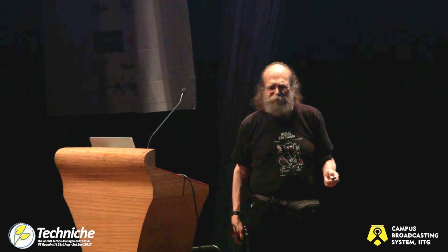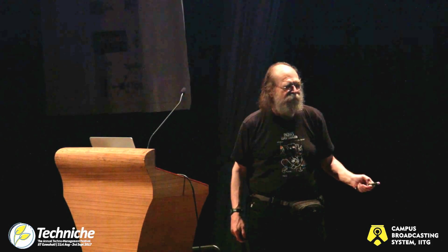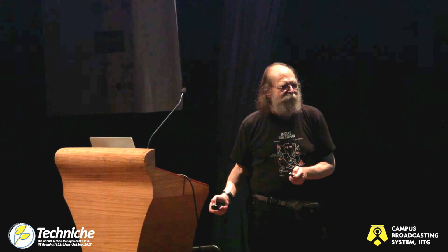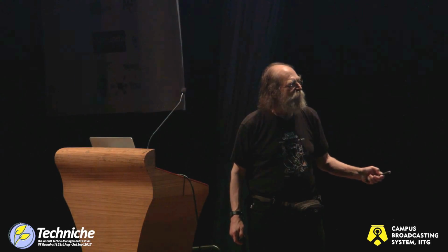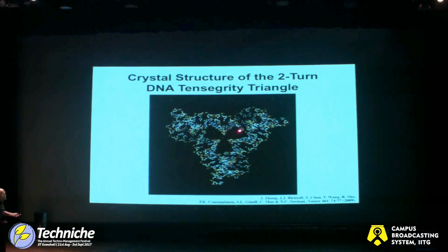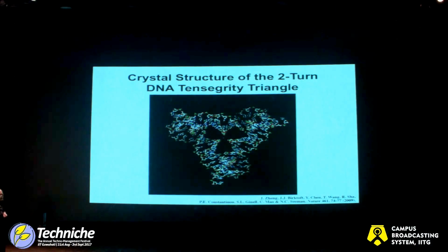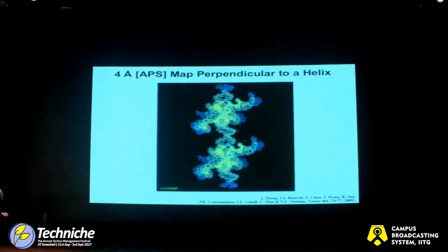But we had to do this crystal structure, and I'm an honest crystallographer, so we made an iodinated derivative and solved these structures by unbiased methods. And then this is the structure of the triangle. This part's in front of the screen. That's in the plane of the screen. That part over there is behind, where this is in front again, and so forth. It's threefold symmetric. And this shows that, in fact, we have the sticky ends holding the different units together right